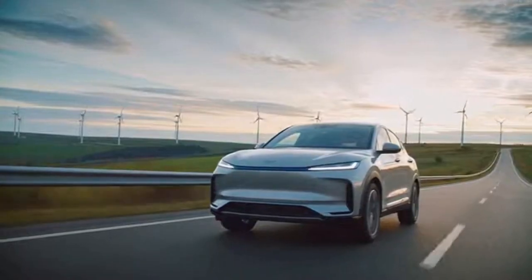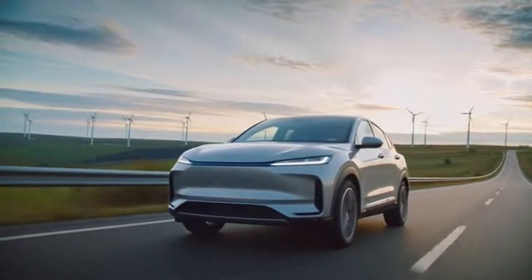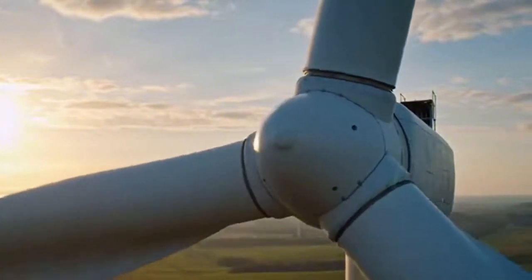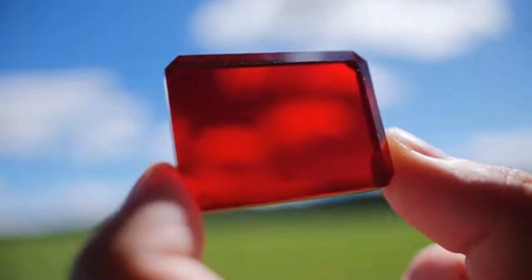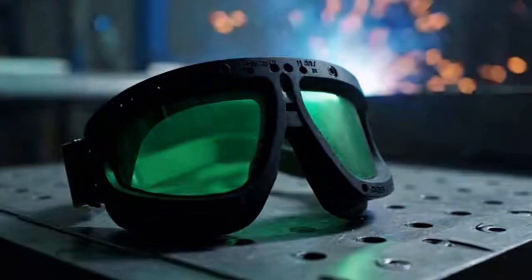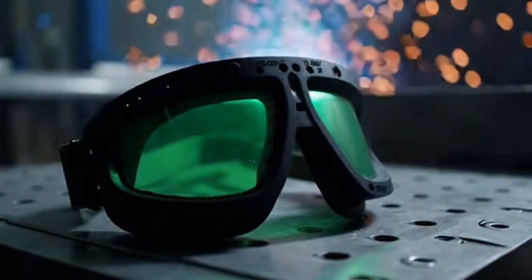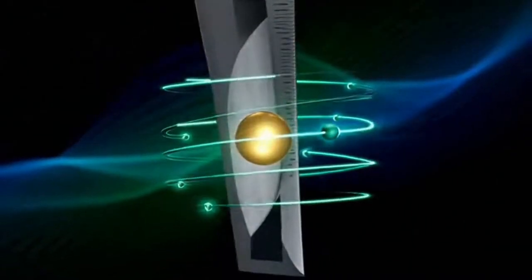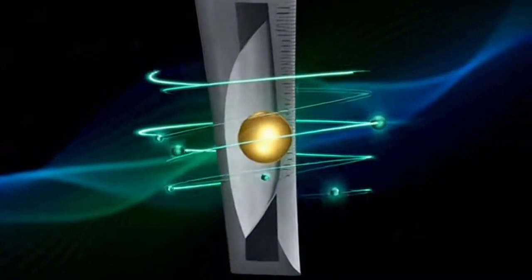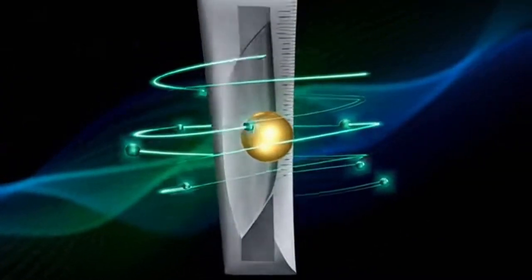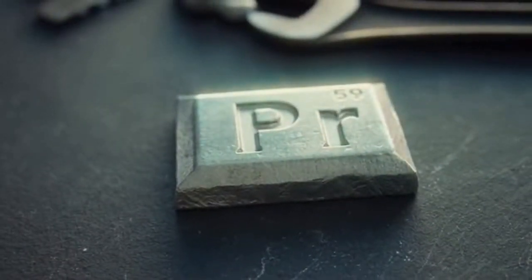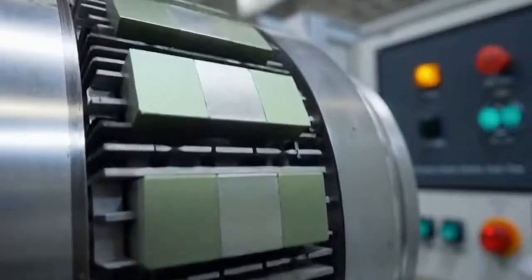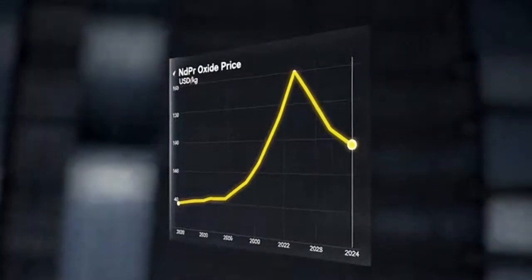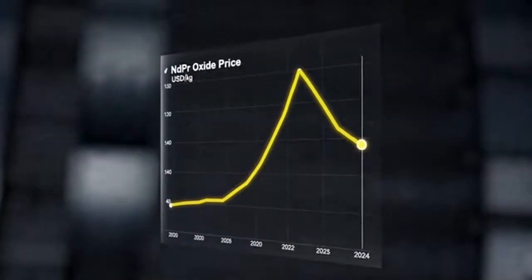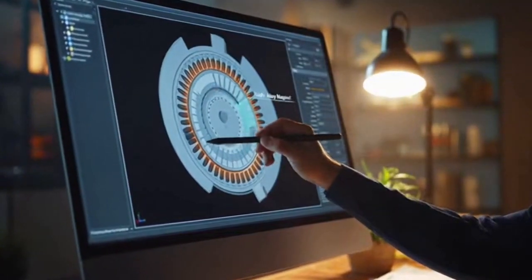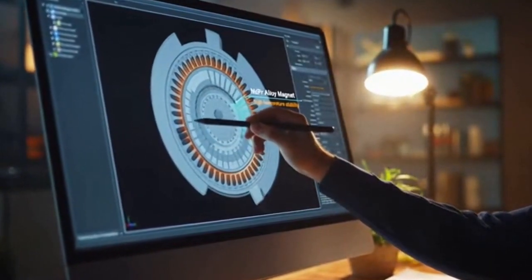Small additions of elements like aluminum, copper, niobium, and gallium adjust grain growth, phase stability, and boundary chemistry. Those additions are not fashion, they are levers. Praseodymium harmonizes with those levers in alloys that target high power density at elevated temperatures. It is not that neodymium alone cannot do the job. It is that the shared job becomes easier when the twin with the greener temperament is in the room. The datasheets will not say it that way.